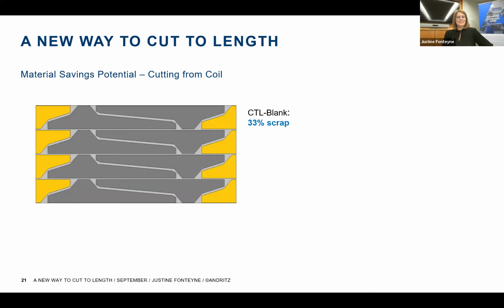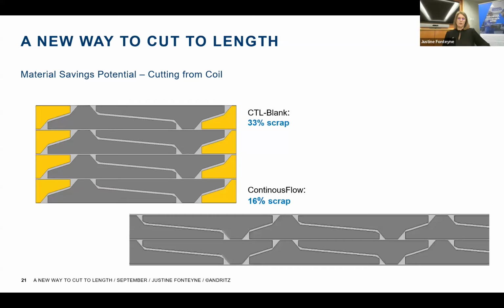The last example is to cut the parts directly from the coil. So this is an example we had with a customer cutting those shaped blanks out of a rectangular blank. And you see on the yellow areas, this is all scrap. So 33% of the actual blank is scrap. And by doing a continuous nesting from a coil, you can already save 17% scrap. So in this scenario, you would just have 16% scrap. And what comes on top with that solution is that we can use a second laser head on our gantry to make it a 2 laser head system.